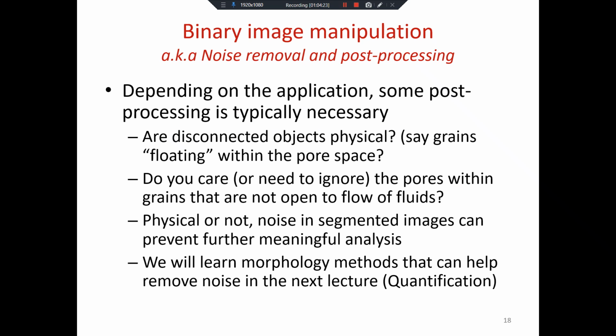Sometimes it's physical, sometimes it's not physical. So those bead defects inside of a bead, they're physical. They're there. You might, for your modeling purposes, want to remove them. And if you want to remove them, you need to be able to find and filter them from your segmented image. So your segmented image is an image. It's a simplified image. It's 0 and 255 in this case. You still might want to process and filter that image.